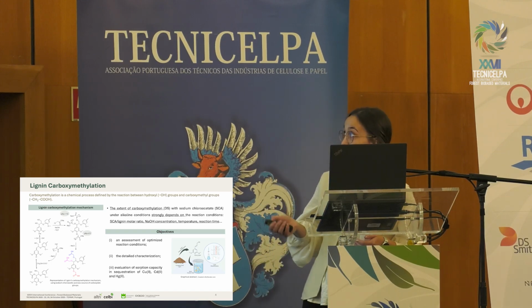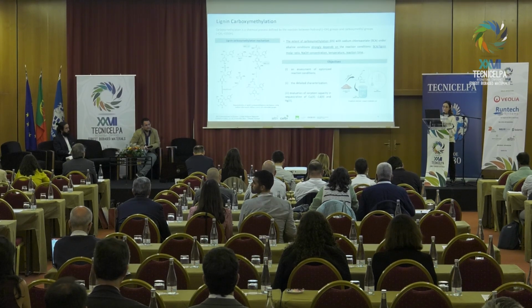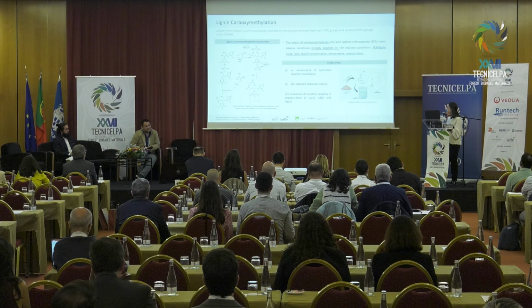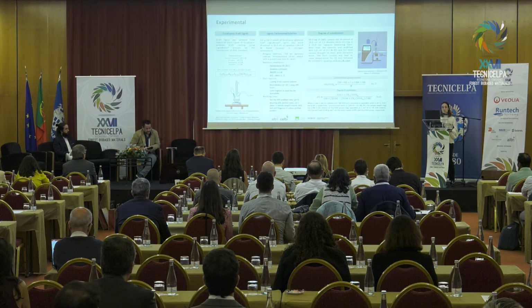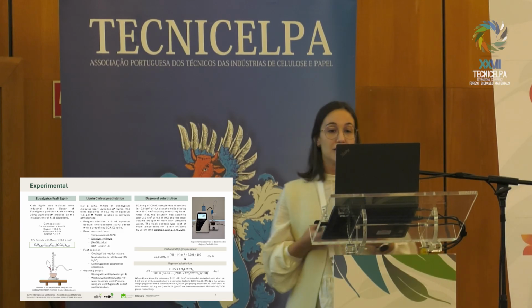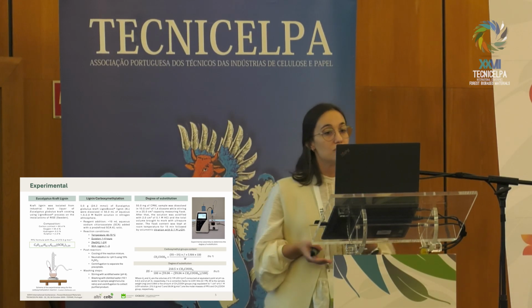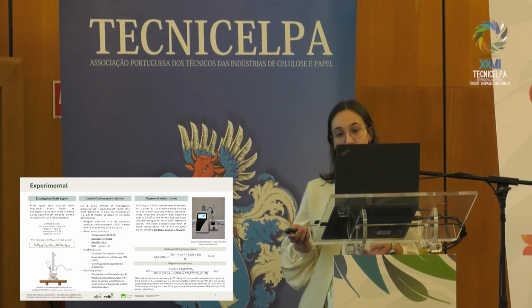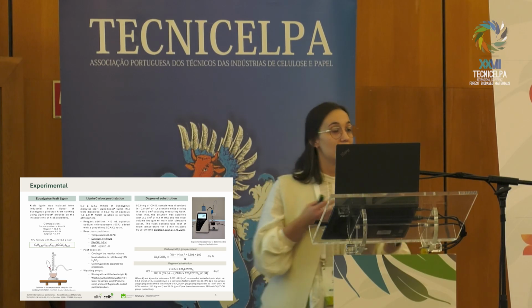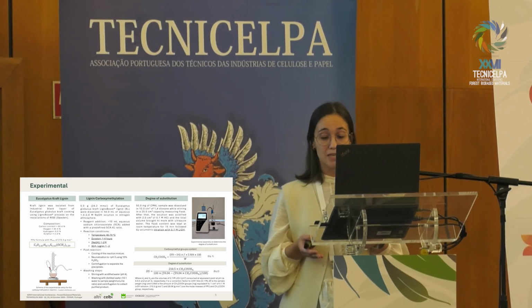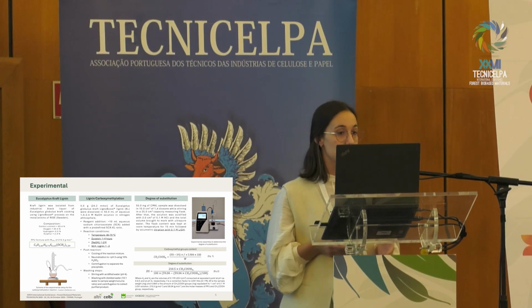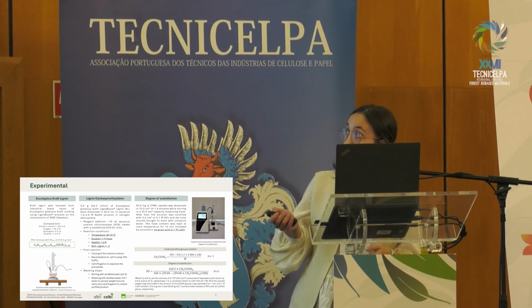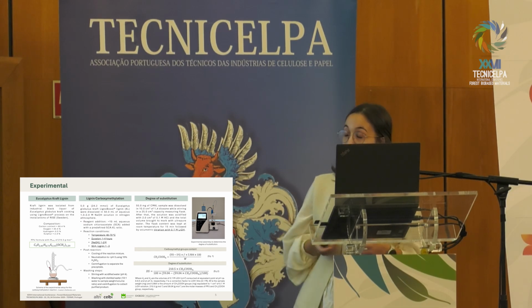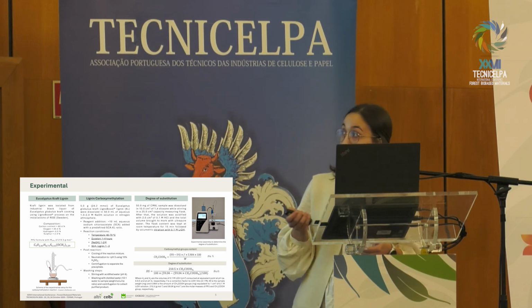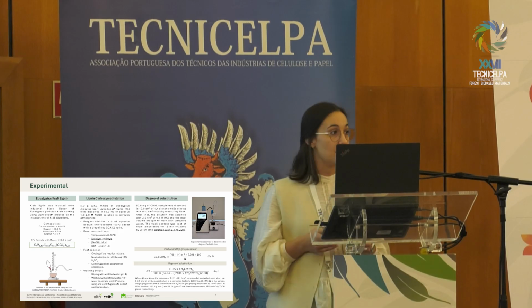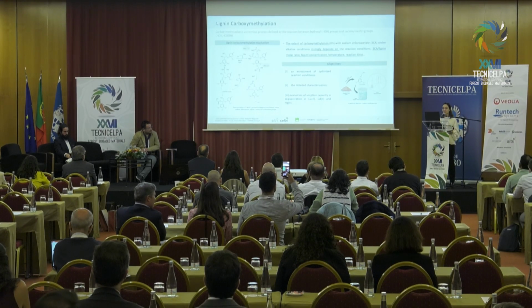So, among several functionalization methods, we focused on carboxymethylation. This functionalization enhances lignin solubility, chelation capacity, and surfactant behavior, making this material suitable for uses like dispersants or biosorbents. Regarding this reaction between lignin and sodium chloroacetate, this occurs via a nucleophilic substitution mechanism where phenolic hydroxyl groups are the most reactive. They are easier to react due to their easier ionization in alkaline conditions, and the aliphatic hydroxyl groups are less reactive, and we don't know for sure to what extent they react.